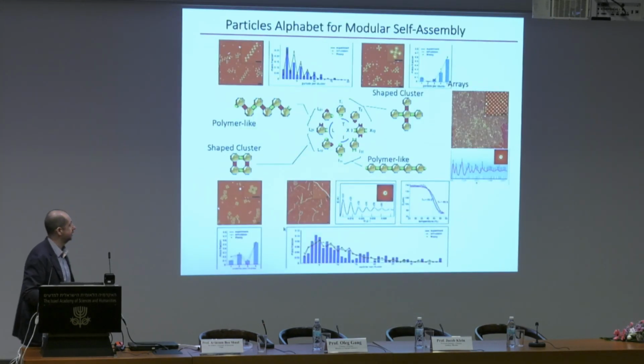So having this in mind, we were able to create, by mixing different types of components, polymer-like structures, either linear or zigzag, also clusters and 2-dimensional ones. I wanted to stress here, what you see here are histograms obtained from AFM, and we can quantitatively understand the formation of those structures by taking into account the hybridization energy and the stoichiometry of the mixing of the bonds.